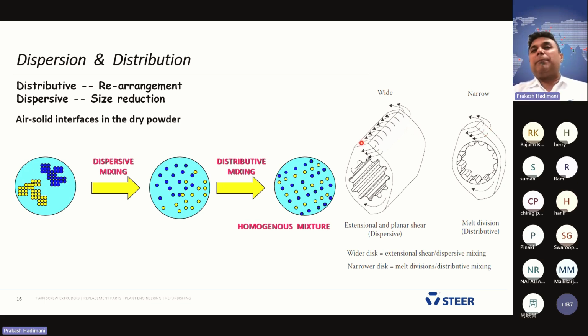It depends on the pigments. You need to select the screws. But when you are using wider kneading to break the particles, you are using more energy to break the particles in the dispersion mode, because that is a tendency of the dry pigments to agglomerate.